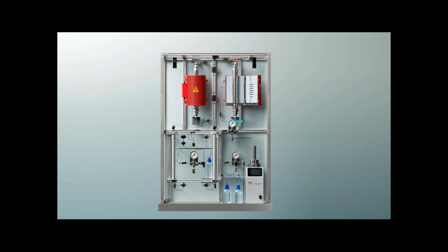The other thing we can do is change the pH over the experiment. In the older equipment, we have to put everything in the first separator, and of course it has to go through the preheater. And we could only put one pH in, otherwise we'd have to empty this out and refill it. Now we're able to put an acid or a base in this, and we dose the brine as it comes through and adjust the pH. So this is basically acting as an acid dosing simulator. And so we can look at silica polymerization rates by adjusting the pH over the experiment.